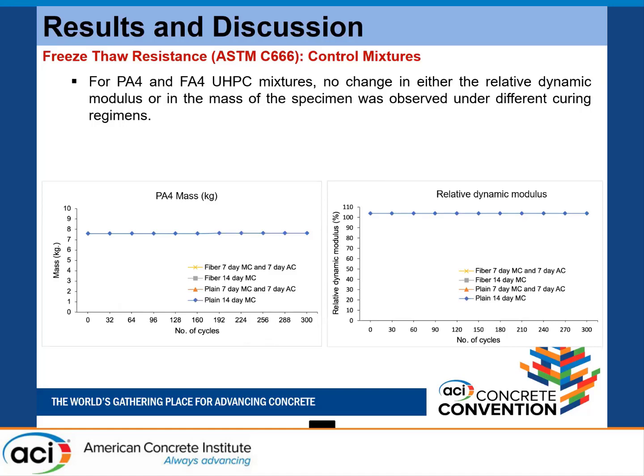These two graphs are basically mass versus number of cycles on the left, and relative dynamic modulus on the right, and these graphs are related to A series mixes, non-slag mixes. There is no mass reduction. That means there is no micro crack formation, no material distress inside. That's an indication.